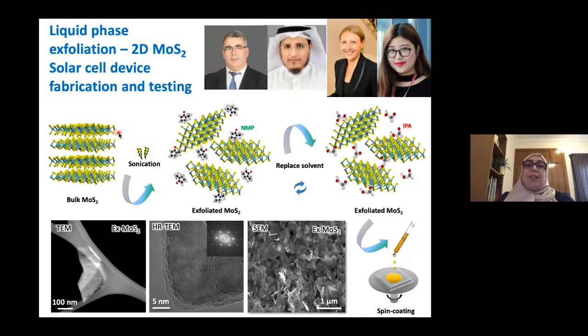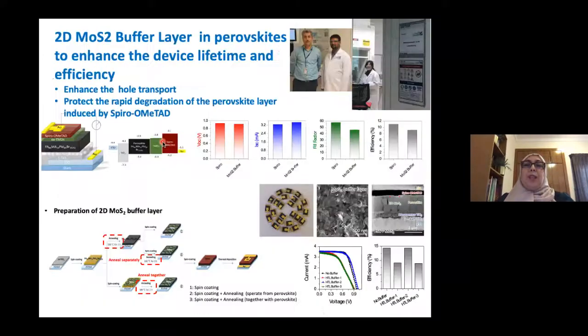It's normal. So as a mitigation strategy, we thought, why don't we try to use these dichalcogenide materials in perovskites to enhance the device lifetime and efficiency. That was based on previous publications that used other types of materials like C60 to enhance the hole transport and protect against the rapid degradation of the perovskites induced by the hole transport material. In that aspect, Jenny came to Qatar. She stayed in Qatar at least 3 months. In her second trip, she was tightly working with Annan and Dr. Beladi, and she managed to generate very interesting results using a molybdenum sulfide buffer layer for the synthesis of these materials.